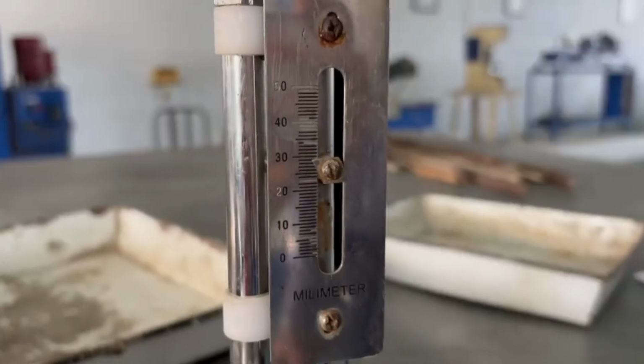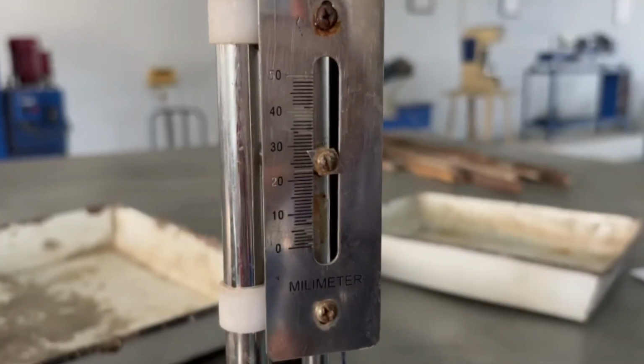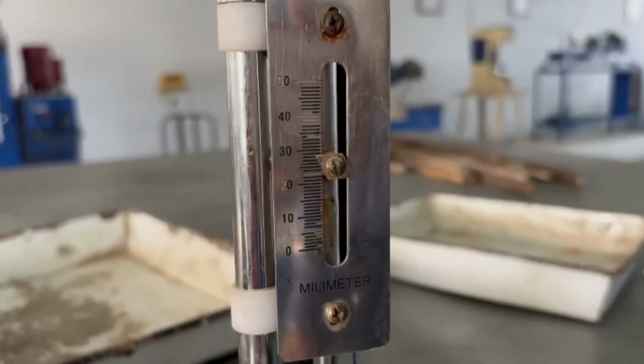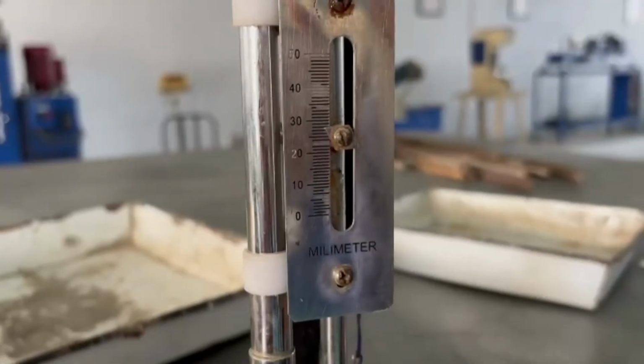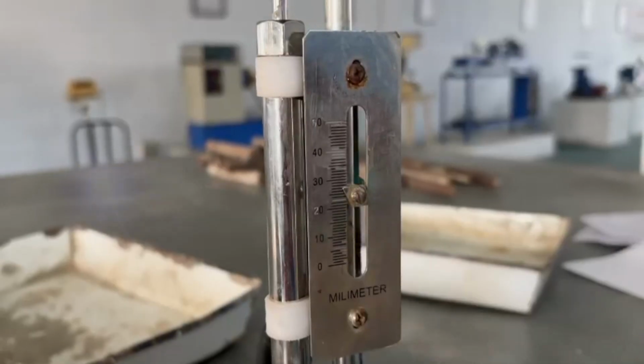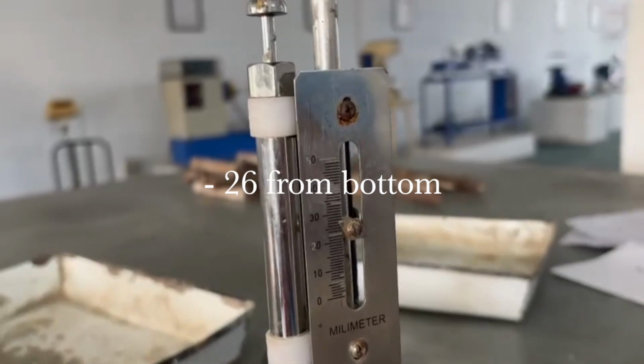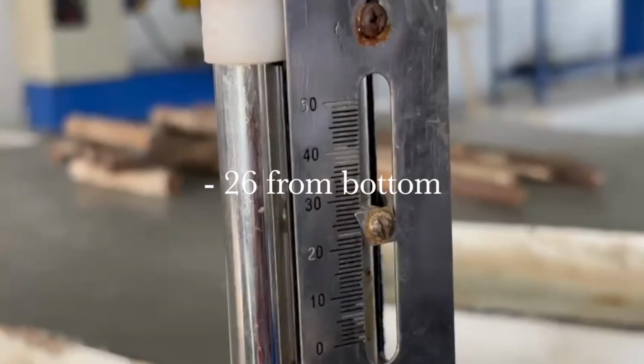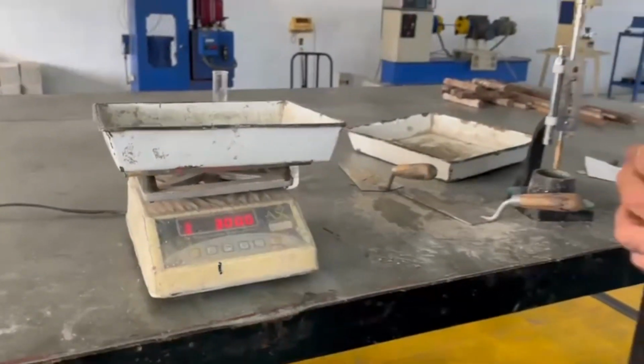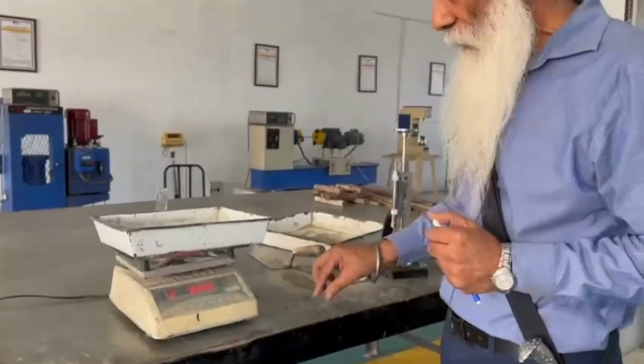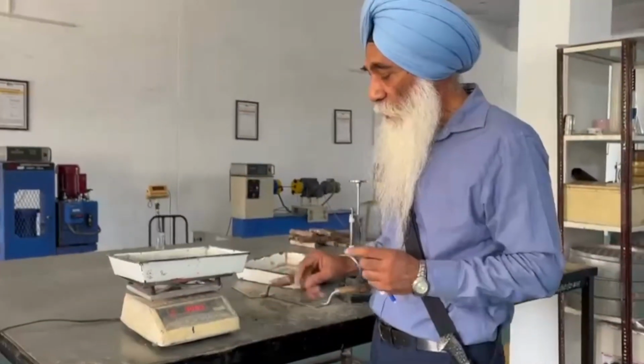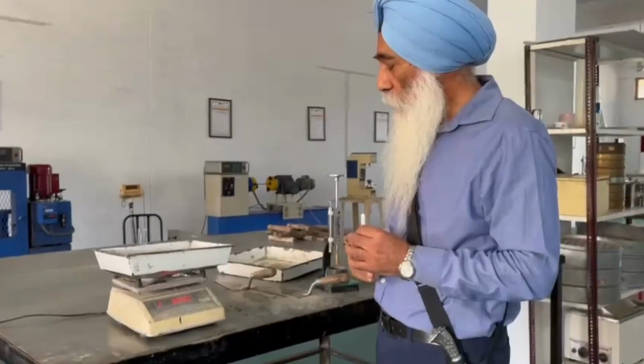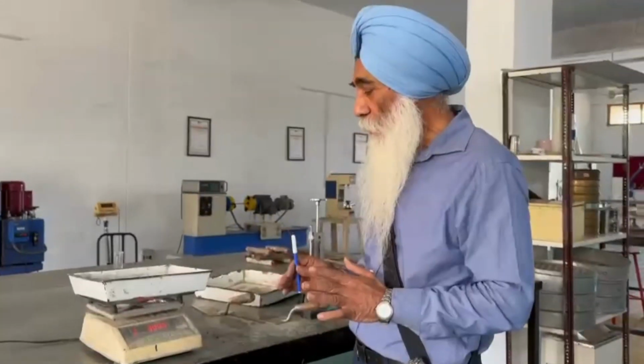It should be 33 millimeter from the top and 7 millimeter from the bottom. Here we can see the penetration is 26. So it means it requires more water. As you have seen in the previous case, the penetration was 26 mm. It means we require more water.